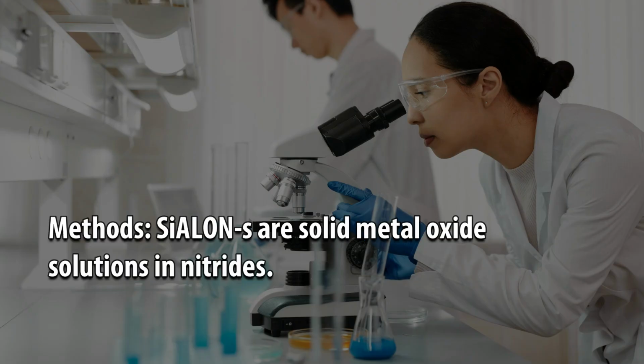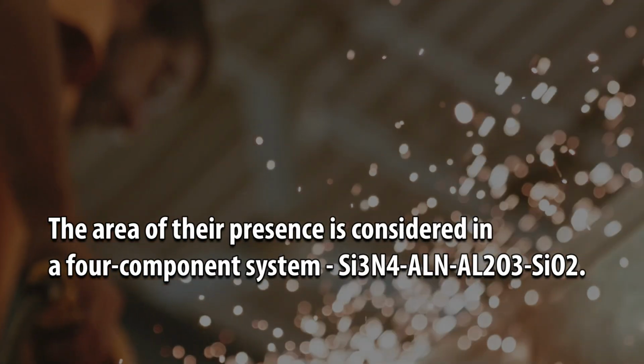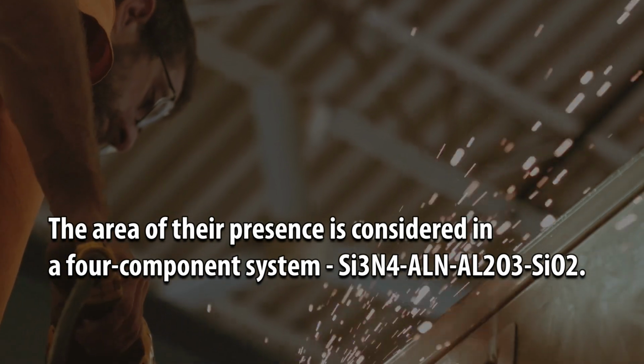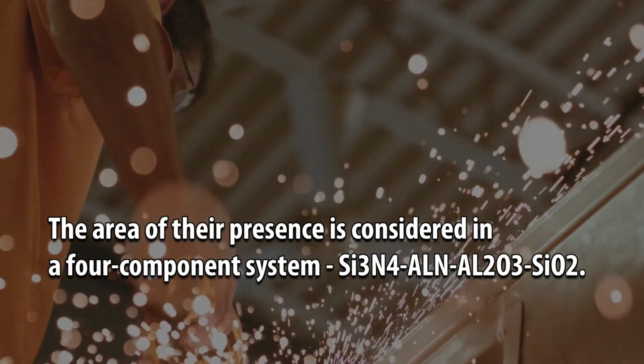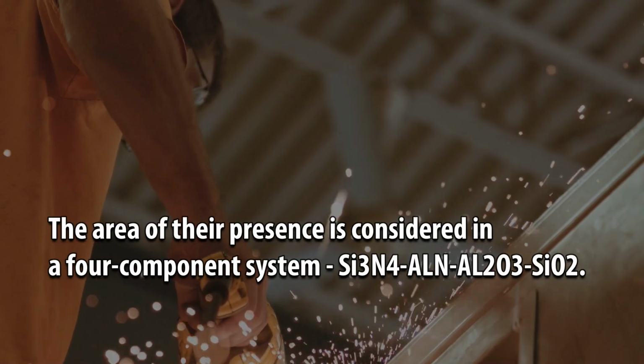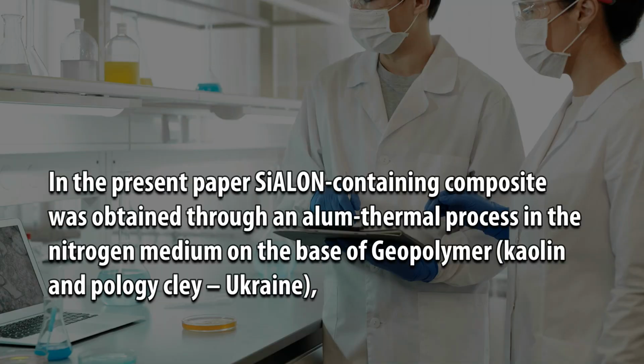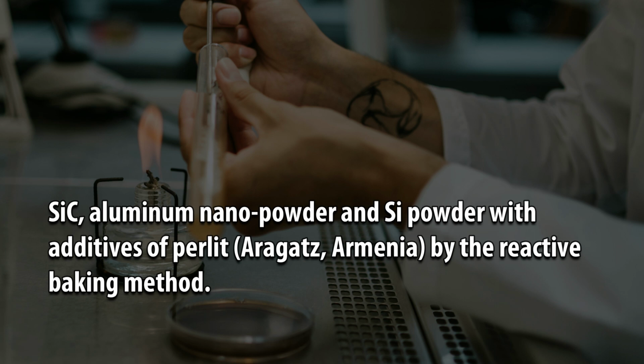Methods: Sialons are solid metal oxide solutions in nitrides. The area of their presence is considered in a 4-component system: silicon nitride, aluminum nitride, aluminum oxide, silicon dioxide. In the present paper, Sialon-containing composite was obtained through an alumothermal process in the nitrogen medium on the base of geopolymer, kaolin and Pology clay, Ukraine, silicon carbide, aluminum nanopowder and Si powder with additives of perlite, Aragats, Armenia, by the reactive baking method.